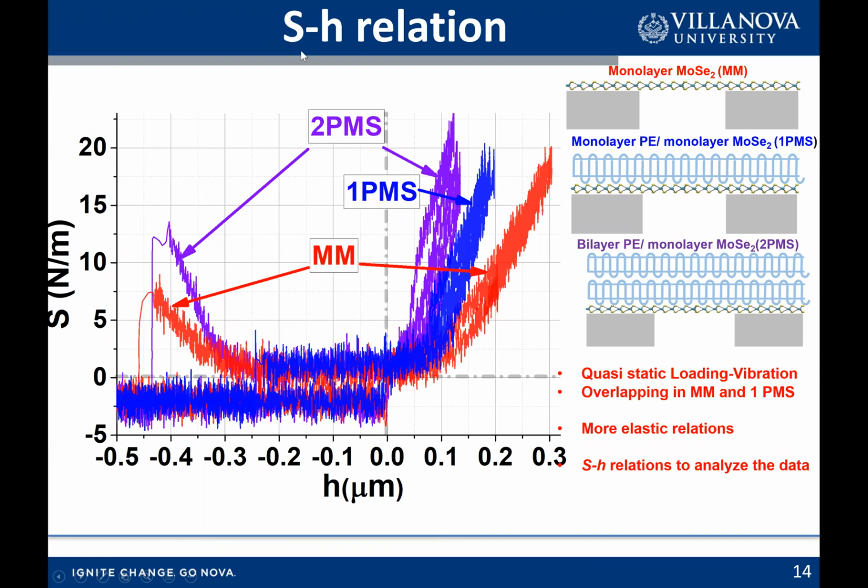Instead of load displacement, we studied the stiffness versus displacement relations. If we talk about the stiffness relations, so there comes the quasi-static loading, and the continuous stiffness measurement is being done in the nano indenter. So we can see that during the load, small oscillations of forces are observed, and that's why we have studied the stiffness instead of load.